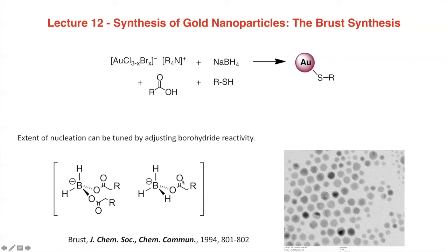So as you knock off hydrides, you end up with less and less reactive reducing agents and slower kinetics, and then larger particle sizes. So clearly precursor limited nucleation in this case, unlike some of the other ones. And that's reasonable because you have a much more reactive hydride source, and the homogeneous conversion of gold salts to gold zero is much faster under those conditions.